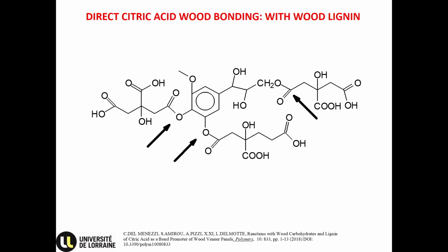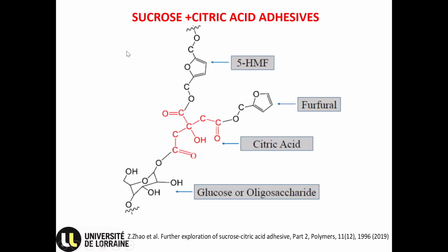And it can be used, of course, more effectively with sucrose plus citric acid, as proposed by Kenji Umemura. And you can produce 5-hydroxymethyl furfural. You can have furfural. The citric acid itself reacted both with the furfural as well as the glucose oligosaccharide. There is a problem with this one, a problem that no one realized. Me too, I didn't realize at the beginning. And when we realized it, we were shocked.